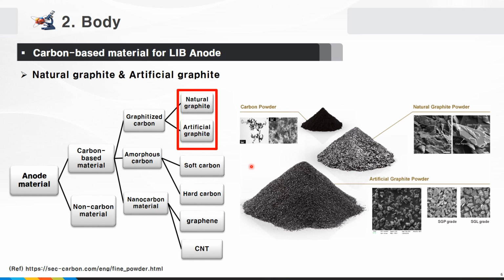Therefore, in the past, artificial graphite was used more than natural graphite due to the low initial charging and discharging efficiency of anode active material for LIB. However, the initial charging and discharging efficiency of natural graphite was improved to more than 90% through surface treatments such as spheroidization and pitch coating of natural graphite, increased the proportion of natural graphite with price compatibilities. This trend will continue in LIB for small electronic devices.